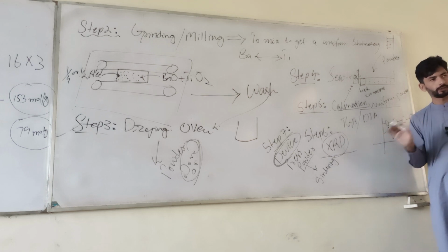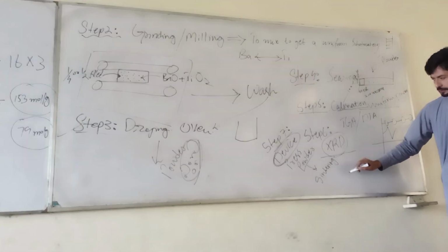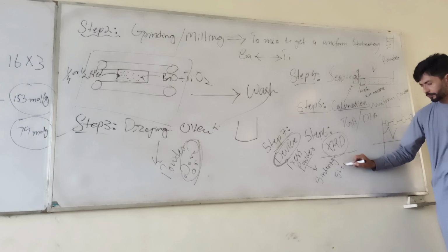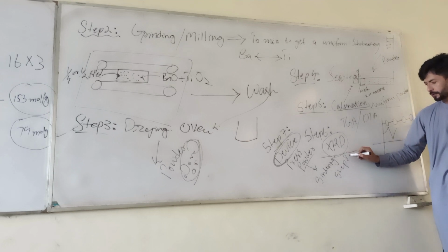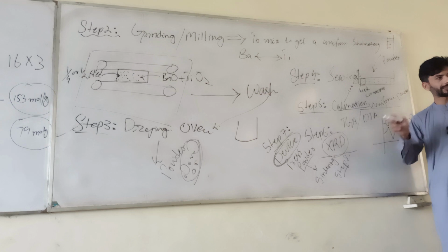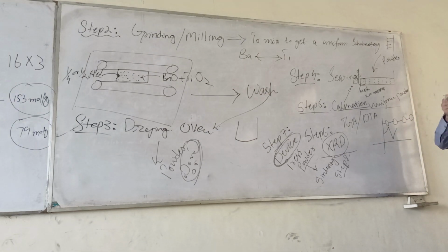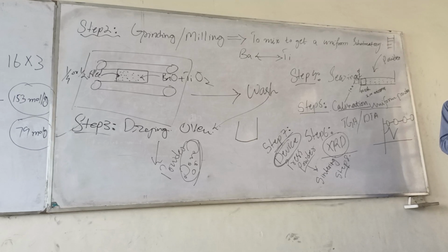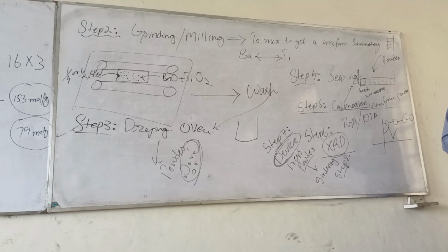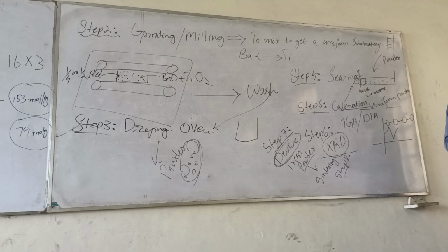Okay? Is it easy? After sintering, here is step number 8. Just coat this sintered pellet with a conductive material on both sides. Usually we use silver paste. Just like coloring your nail, the same is the method to coat the silver on both sides of that pellet.